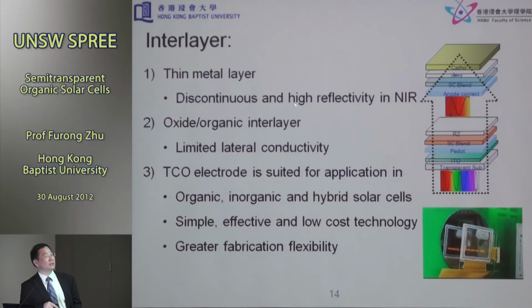Now the reason why semi-transparent organic solar cells come in is that a semi-transparent organic solar cell unit is essentially needed for application in tandem solar cells. Okay, so now you can imagine that if I remove the top part, only focusing on this cell, it is actually a transparent solar cell. Okay? It only absorbs what's needed. So you can carefully select the material, for example, one that only absorbs near infrared, and you design a near infrared mirror here, so the visible light can still penetrate through the entire stack, but the cell absorbs the light and generates electricity. So this is something we call transparent or semi-transparent solar cells, depending on the material that you use.